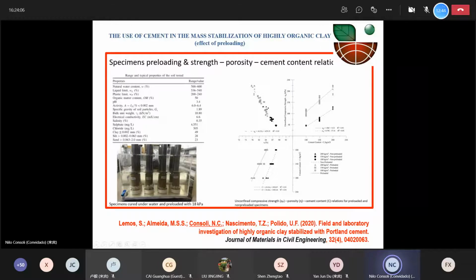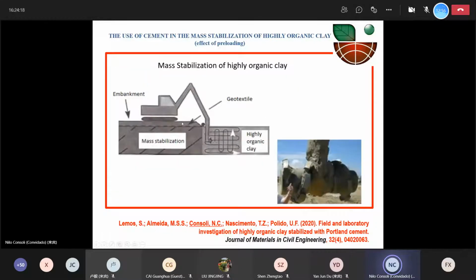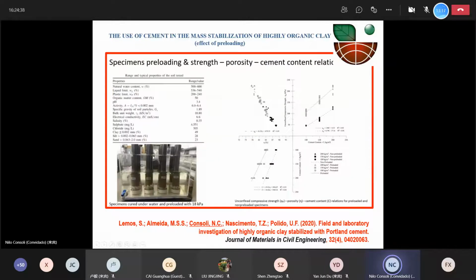And so we tested in the lab the idea of inserting different amounts of cement, and also putting a preload on top of it. This preload is because of the embankment that is usual to put on top, because of the difficulty, if you don't have it, of reaching the position to improve it. Also, you have a geotextile on the bottom. So usually the thickness of this embankment is about 1 meter. So we were also dealing with this, in the lab, with the situation that happens in the field.